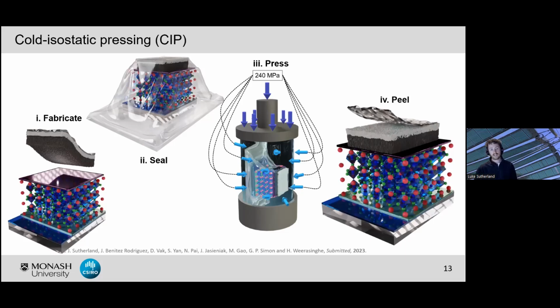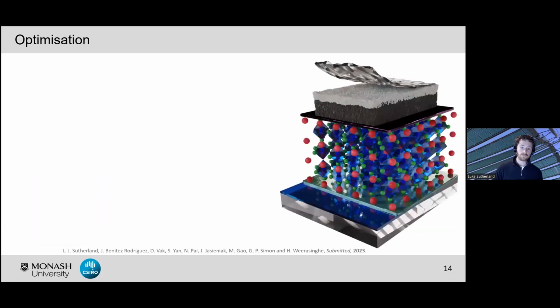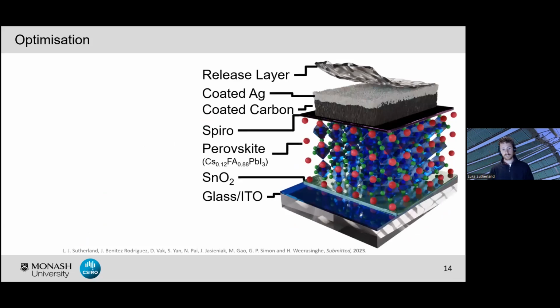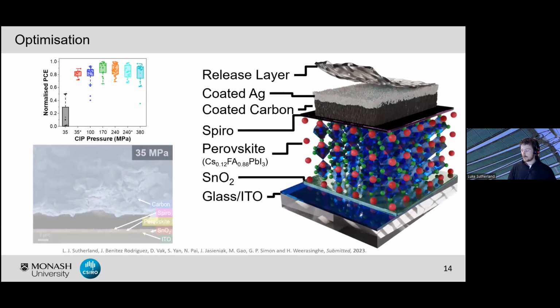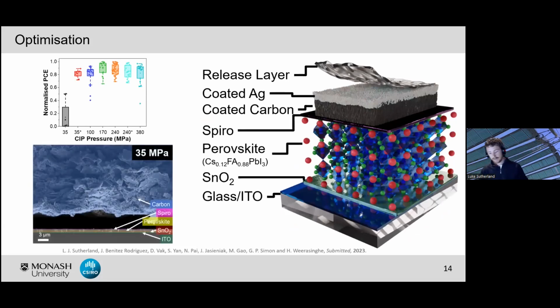So readily scalable technique. It's also used for industrial applications in terms of large ceramic molds and things like that. Anyway, so this is our final device type. So using tin oxide and spiro as our charge transport layers, similar to what we did in our previous work. And as we found using the calender press was that establishing a good connection between our carbon electrode and our underlying device stack is absolutely critical in obtaining high performance.